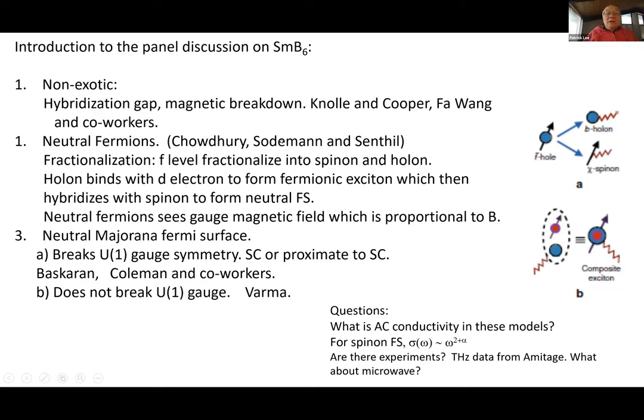The second one is a neutral fermion picture—you need fractionalization. The idea is the f level fractionalizes into spinons and holons. The holon binds to an electron to form an exciton, but this will be a fermionic exciton which has the same quantum number as a spinon. So at the end of the day you get some kind of spinon Fermi surface. This probably is more plausible in the case of samarium hexaboride but less so in tungsten ditelluride.